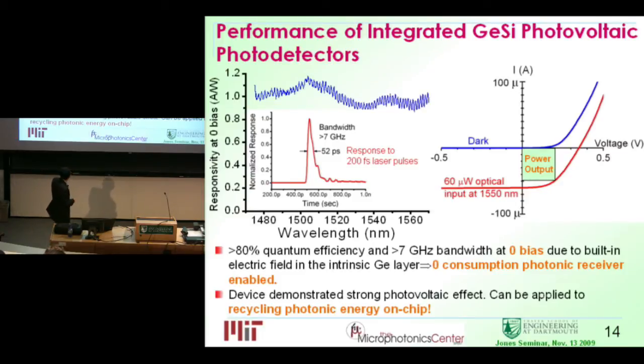Okay. So this device demonstrates a strong photovoltaic effect. It can be used to recover and recycle photon energy on chip. Whenever you have scattering, you can put it nearby and recover some of the scattered optical power. You cannot do the same with electronics, because when you generate heat, it's very hard to recover it, because the heat temperature is not high enough. So you can use thermoelectrics to recover some of it, but the efficiency is much lower than the photonic approach.